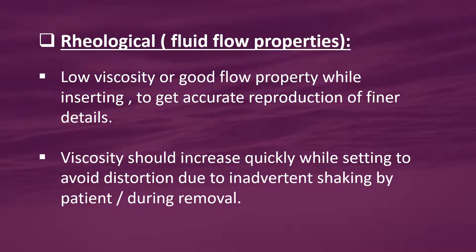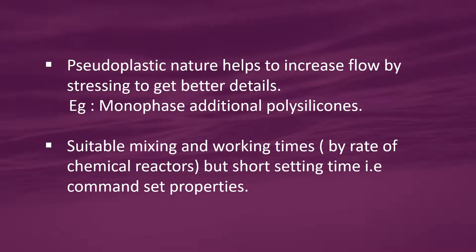Next, rheological or fluid flow properties: it should have low viscosity or good flow property while inserting, to get accurate reproduction of finer details. Its viscosity should increase quickly while setting to avoid distortion due to inadvertent shaking by the patient or during removal. It should have pseudoplastic nature, which helps to increase flow by stressing to get better details — for example, monophase additional polysilicones. It should have suitable mixing and working times determined by rate of chemical reaction, but a short setting time — that is, command set properties.